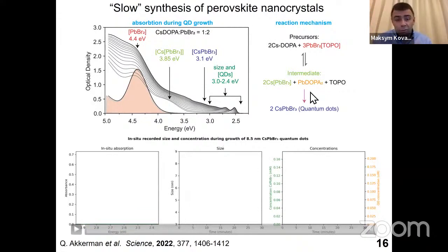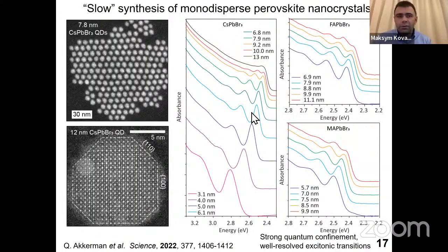The curse, of course, is that you have to do it rapidly, because otherwise nanocrystals after the growth will start coalescing and recrystallizing to bulk material. In this case, right after you reach the plateau in the nanocrystal formation, you add the ligand of your choice, and you can stabilize the nanocrystals. Any ligand that we used before, as well as any ligand which we will discover in future, can now be tested in a very rational manner through this approach. So this brings me to the surface